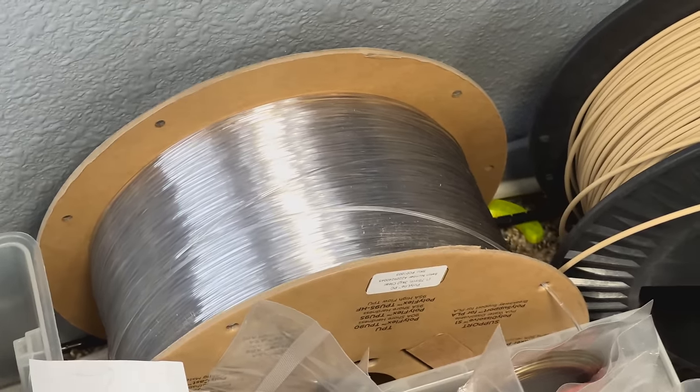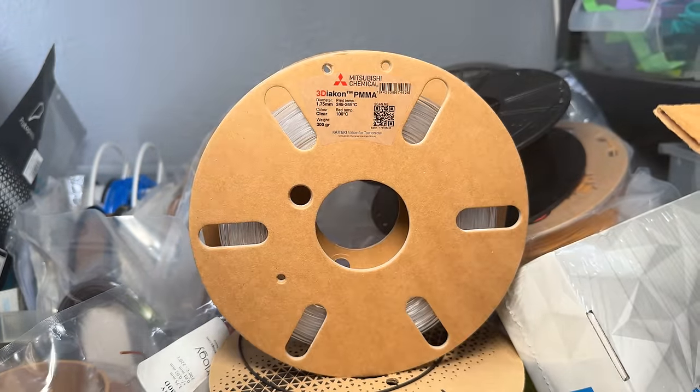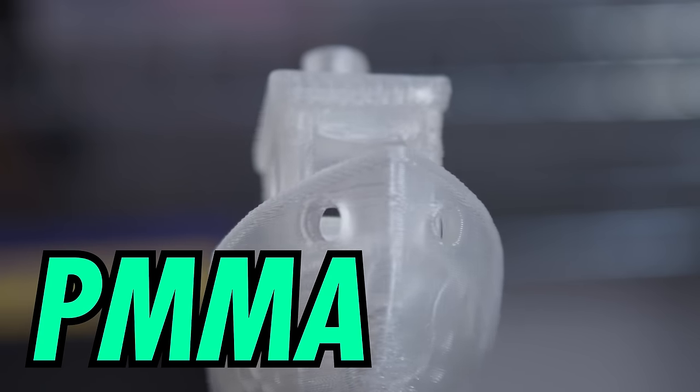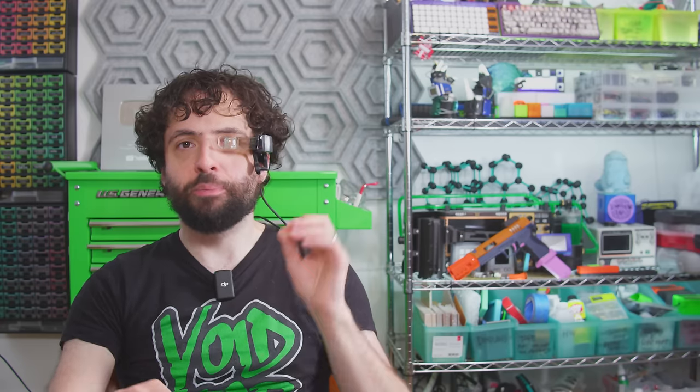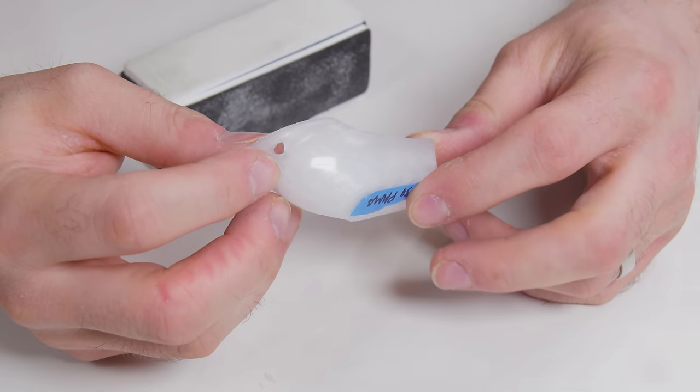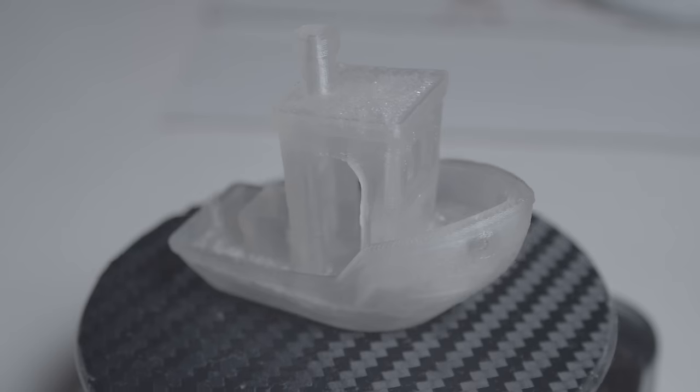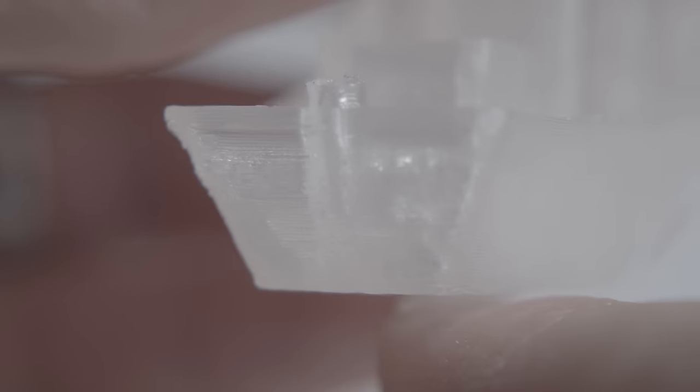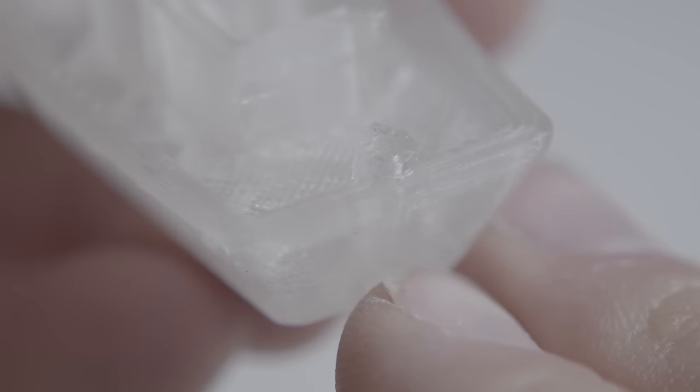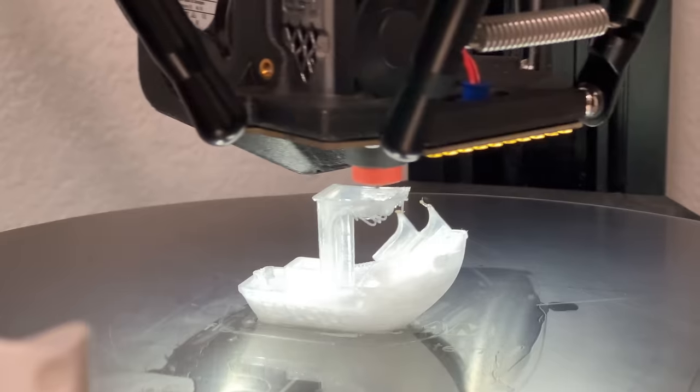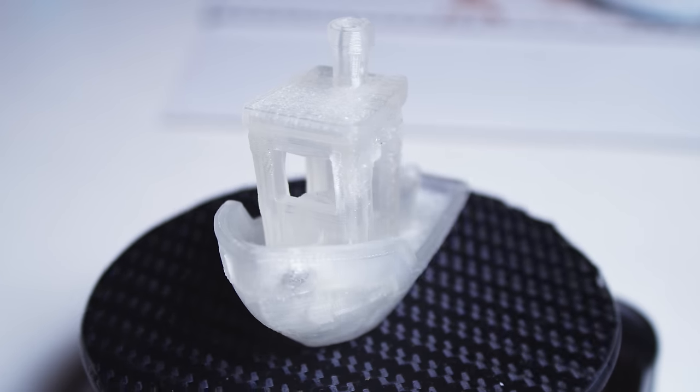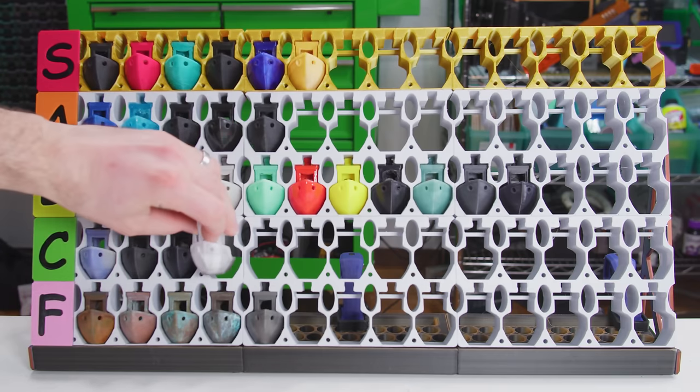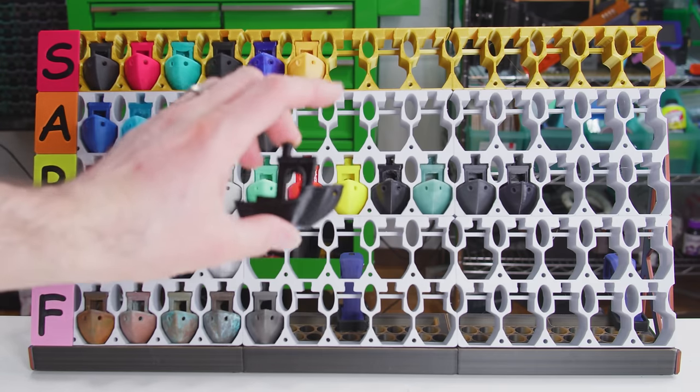Polycarbonate is also crystal clear. In fact, the only thermoplastic with better optics is our next filament, PMMA. Polymethyl methacrylate, also known as acrylic, plexiglass, perspex, lucite, and like a thousand other brand names, is almost always sold by the sheet. But even in filament form, PMMA's clarity is truly incomparable. You can even buff it to a frosted or polished surface. Since it has great resistance to UV, acrylic can even shine in direct sunlight. Unfortunately, PMMA sucks as a filament. It has terrible bed adhesion, crappy layer adhesion, and high thermal expansion, so prints are likely to fail during or even after the printing process. It's also extremely brittle, and absorbs water super aggressively, while taking a very long time to dehydrate. It's a terrible filament, but it looks really, really gorgeous. It's not that expensive, and compared to other outdoor filaments, it's not actually that demanding. I'm gonna put PMMA in C tier. C for clear. Every non-transparent PMMA gets an F, because I truly do not know why these exist.